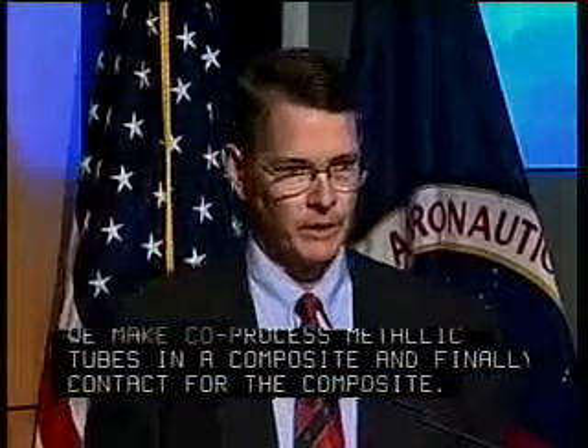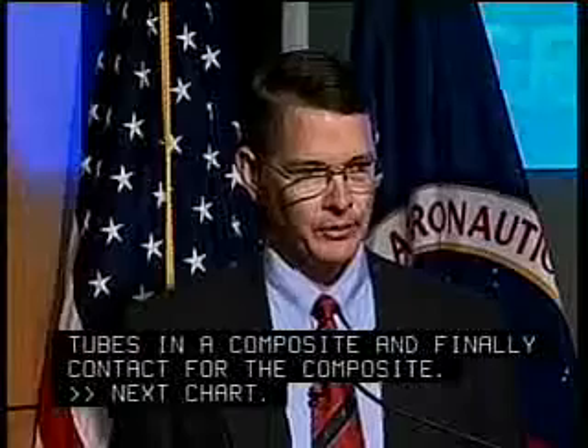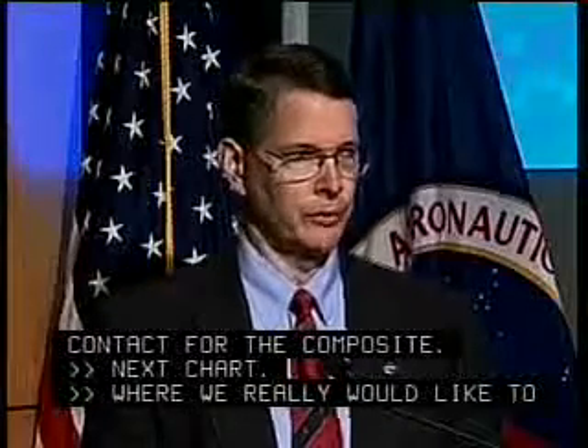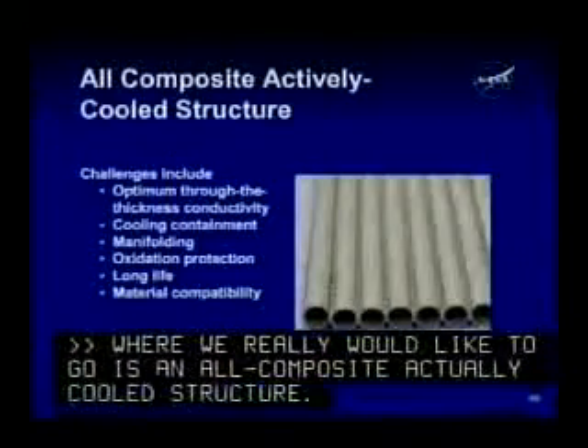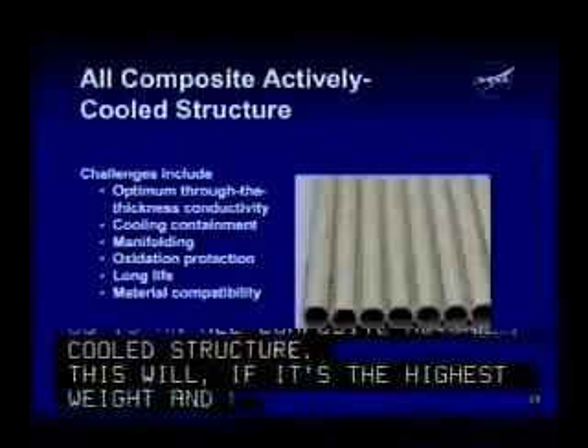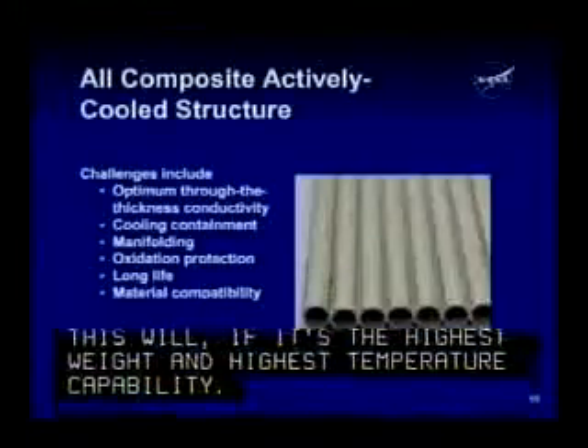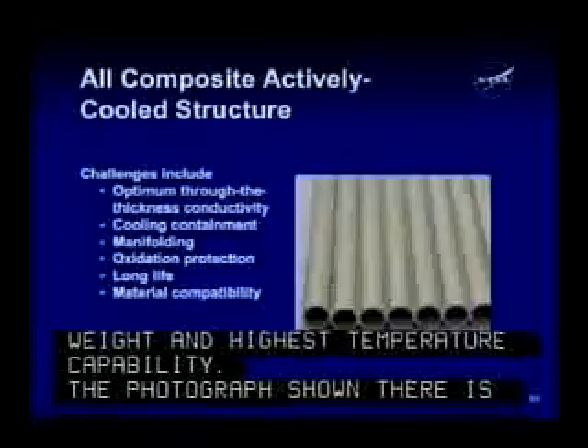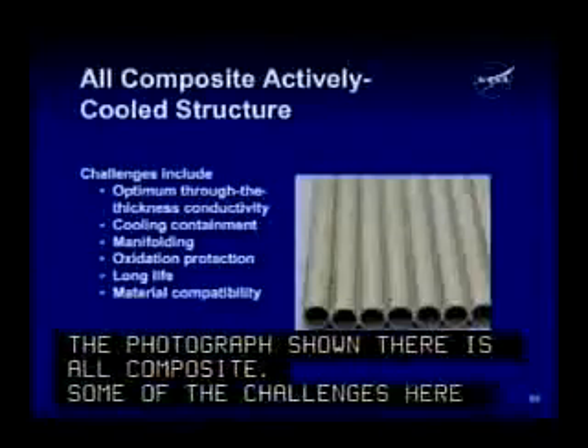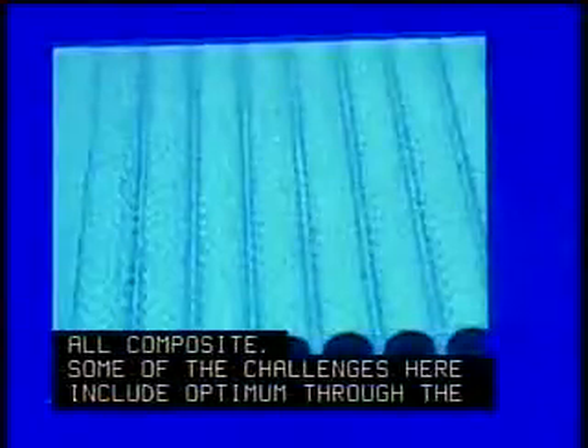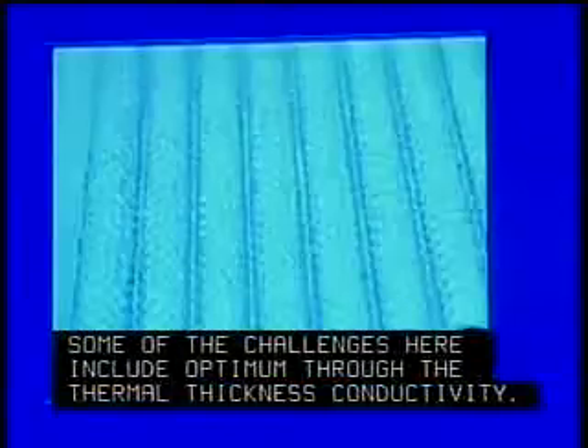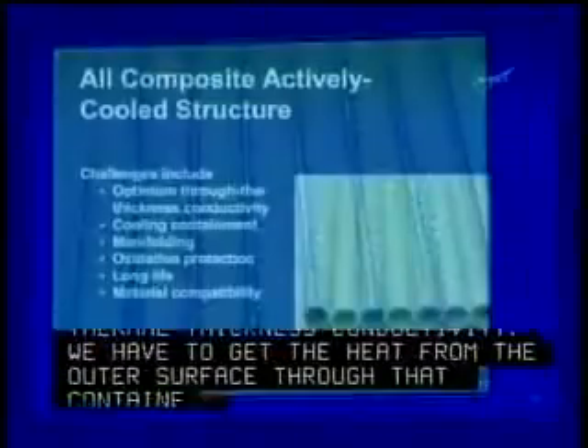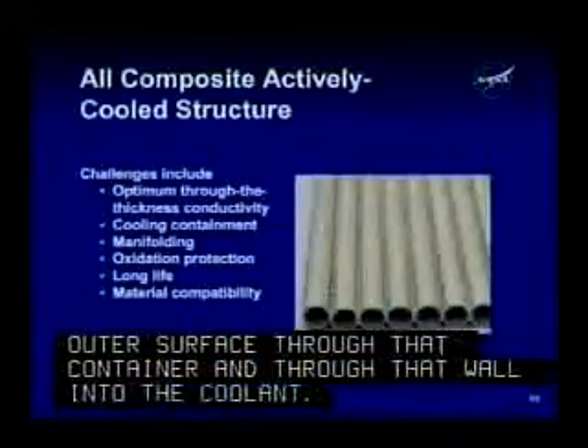Next chart. Where we really would like to go is an all-composite actively cooled structure. This will give us the lightest weight, highest temperature capability. Photograph shown there is all composite. Some of the challenges here include optimum through the thickness thermal conductivity. Again, we've got to get the heat from the outer surface through that container, through that wall, into the coolant. The containment to the cooling is an issue.